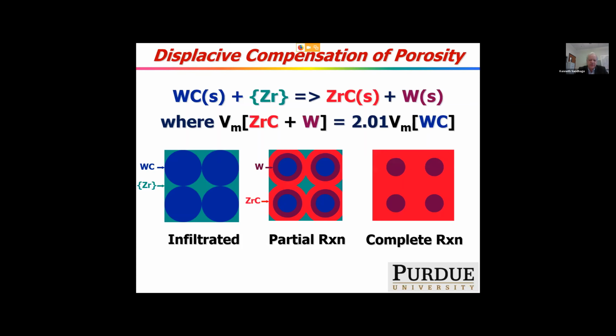And the process continues until the pores are filled because of the doubling of internal solid volume due to this internal reaction. And so it's a process that allows us to make dense, net-shaped parts without the common problem of shrinkage. You can certainly make ZrC-tungsten composites by mixing the powders and sintering them, but in that case, the whole part collapses to fill the pore space, and it's difficult to make complicated shape, distortion-free parts that way, as opposed to this approach.